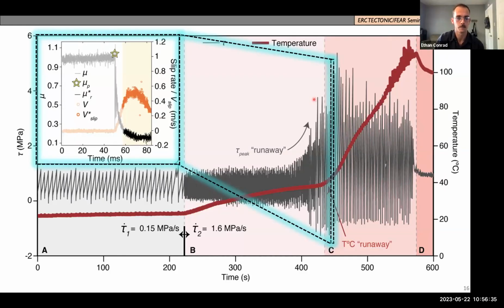Sorry, it's Chris. I just wanted to further clarify that point. So the feedback that you control the loading rate, right? And the feedback that you have on that is a servo controlled system, so that you really try to control the load, because actually it seems like you probably just control the rate, I suppose. Oh, right. Thanks again for this clarification. We're just controlling the rate, and the slip velocity, and when slip occurs, is a function of the relationship between the energy flux that's provided from loading the spring to the interface, and how you dissipate that energy flux after slip. So we're only controlling the rate of loading, and we're calling it energy control because we're controlling how that spring is loading, and thus the rate of change of energy that's being accumulated in the spring. Yeah, it makes sense.